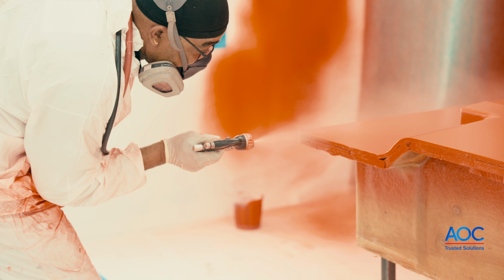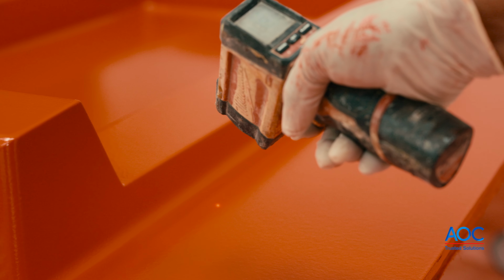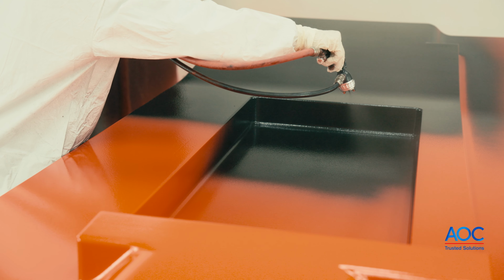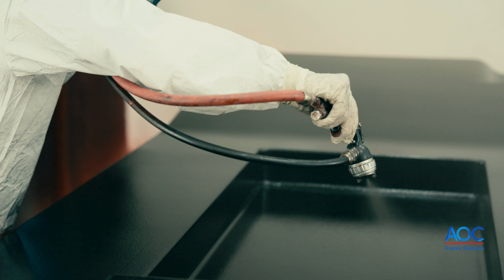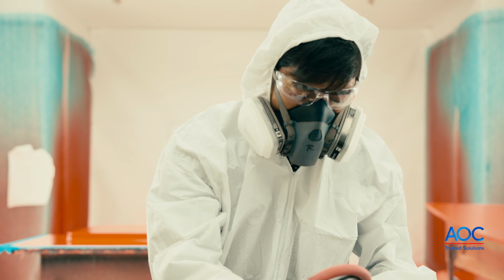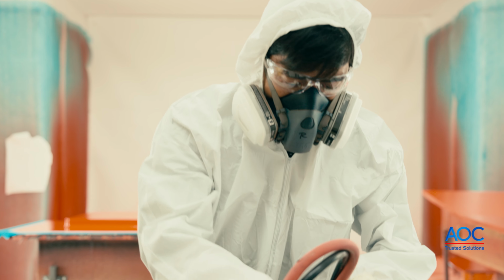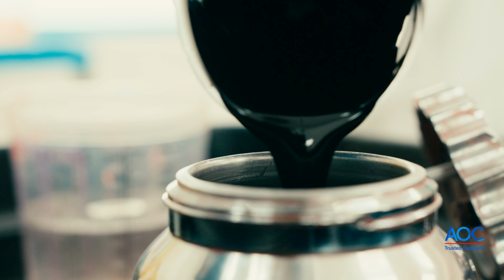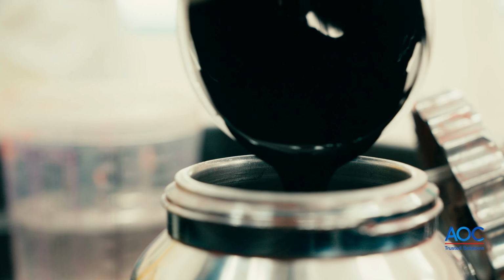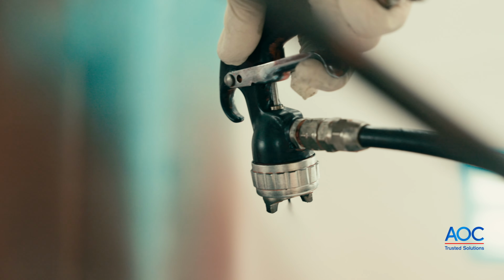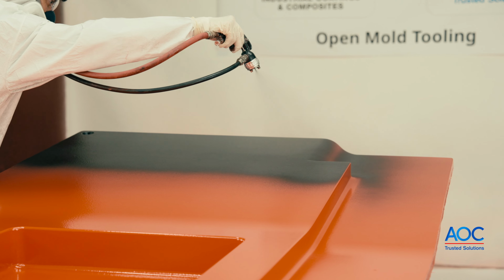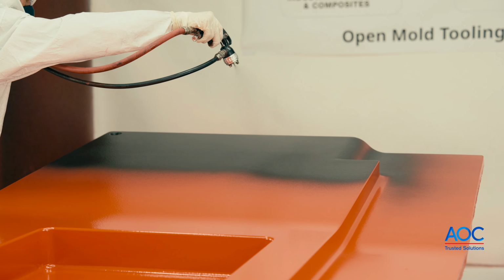Inspect for full cure before applying the second gel coat layer. If you find uncured or wet areas, allow more time or remove and reapply the layer. Once the first layer is cured, you'll then apply a second layer of a different color gel coat, or alternatively, a barrier coat if extra protection is needed for the tool. Ensure the second layer is also applied at 20 mils thick.